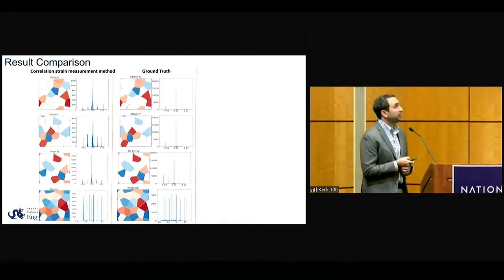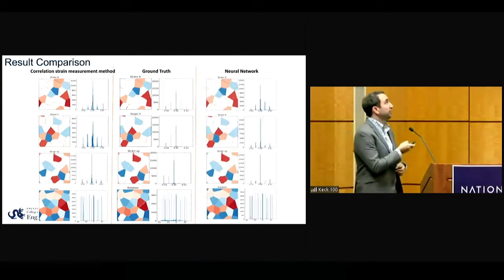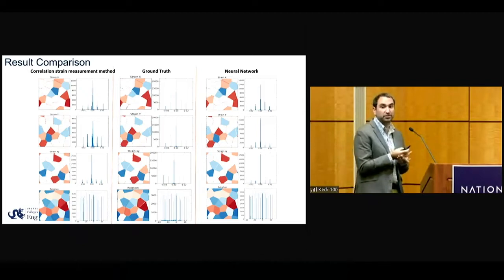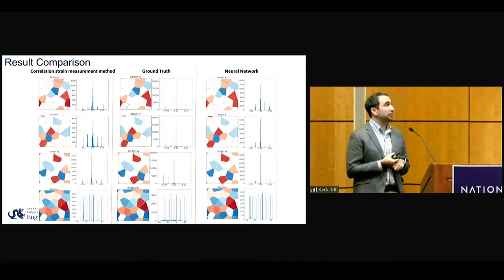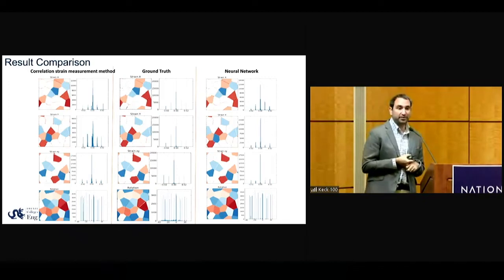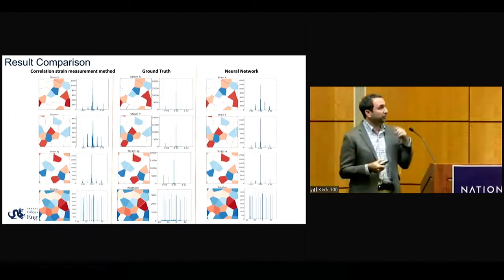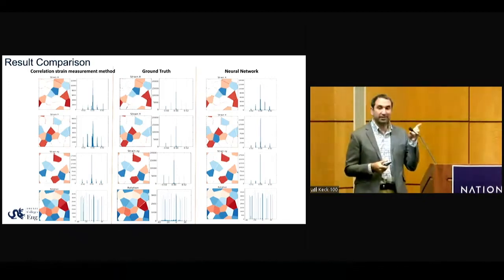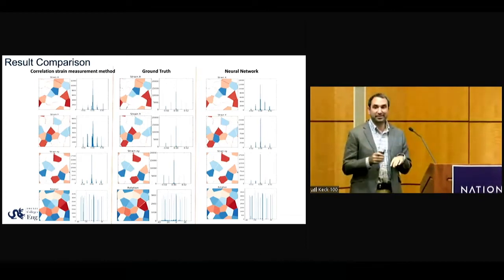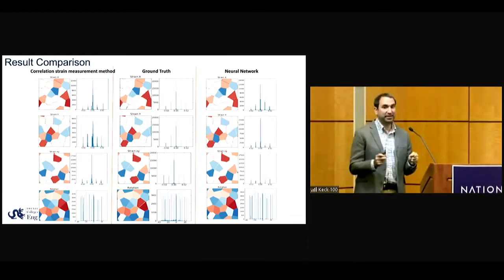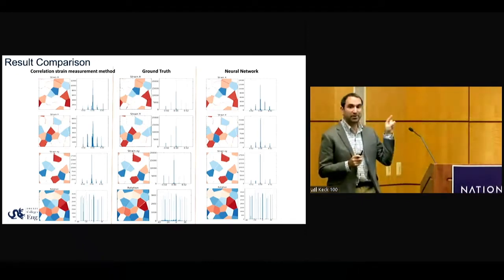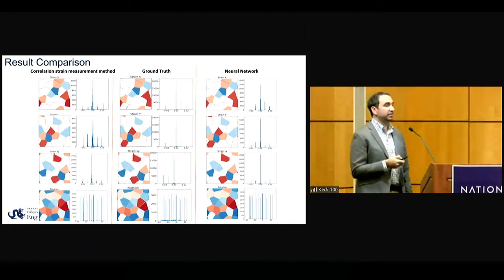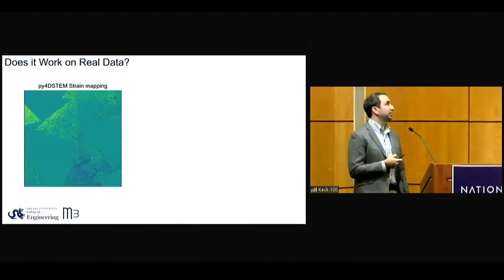But then we should really compare it to the ground truth. If we look at the left, we show the best from py4DSTEM. When we look at our neural network, we're getting much sharper peaks, much sharper distributions. That's saying that we're doing a much better job than the conventional algorithms at actually learning the strain. And the cool thing is that our neural network is giving us the real strain value. It's trained unsupervised. We don't give it any labels, but it's learning the number for the strain because we included the physics in it, which is the physics of an affine transformation.